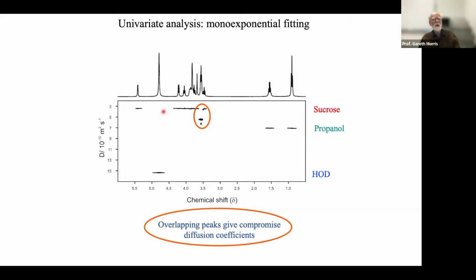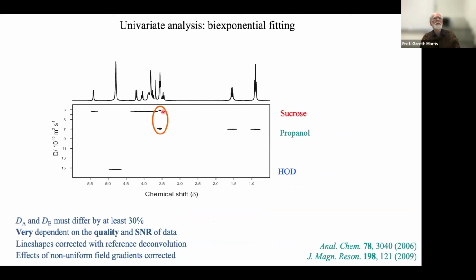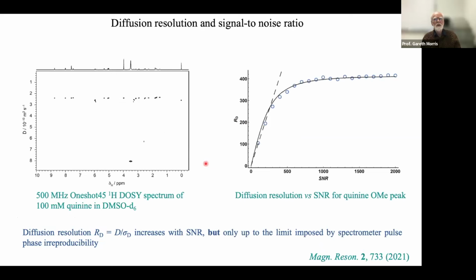Just one more thing about the bi-exponential fitting. I said it's very dependent on the quality of the data and the signal-to-noise ratio of the data. But these data were 25,000 to one, and provided you've a reasonably concentrated sample, that's not too challenging to get. But I said that that's far more than is useful. The reason is that the uncertainty in the signal decay that we measure is determined in part by the signal-to-noise ratio, how much noise there is in our FIDs, and in part by how good our measurements are, in particular, how reproducible our measurements are.